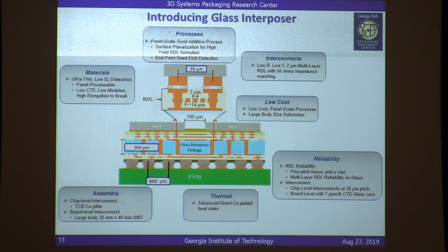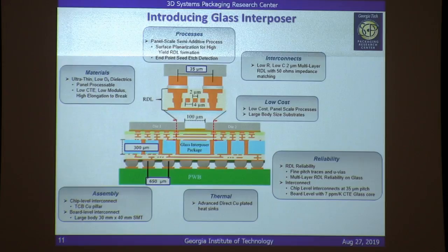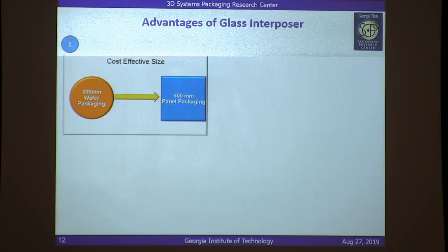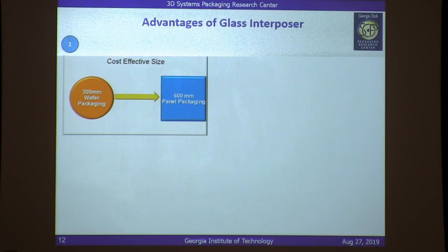The argument is that this structure, even though it has many challenges, gives you opportunities you'll never get with most other technologies — especially for very high-density wiring. PRC has been working on this for five to six years. One major advantage is that glass comes in very large panel sizes — square panels, not circular like a silicon wafer. With these large panel sizes, you can build many substrates in parallel, dice them up, and the cost per substrate can actually be low.